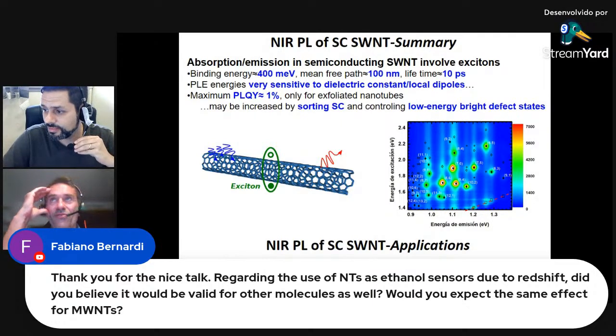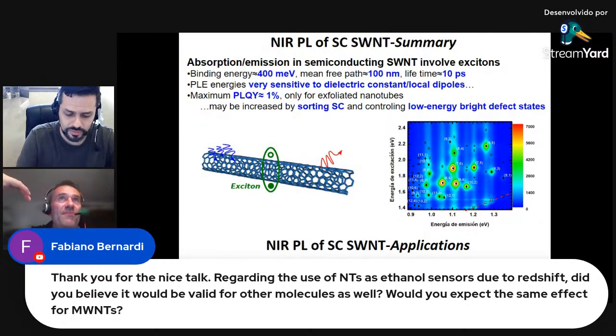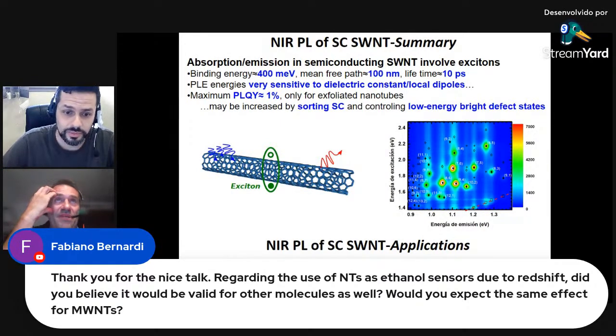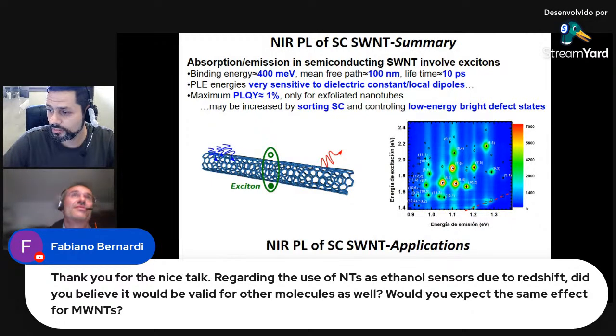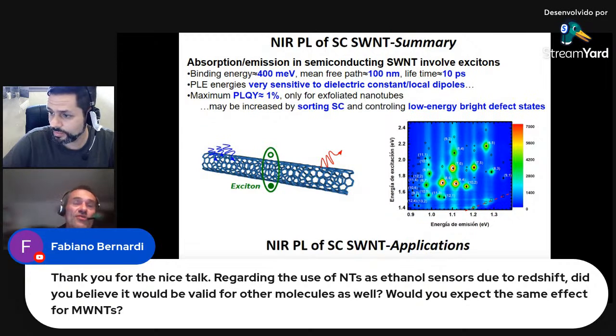Okay, so hi, Fabiano, and thank you for your question. Yes, it's clear that when you start from nanotubes dispersed in vacuum, you have the most blue-shifted spectra that you can expect. And as soon as you adsorb some molecules and form some dipoles on the surface of the nanotubes, you will expect a change in the photoluminescence, which will basically always be a redshift. So whatever molecule you adsorb on the surface, you should be able to detect it. Then, of course, it's not very selective, so there is no way of knowing exactly what kind of molecule you adsorb. You can only calculate the effective dielectric constant, the effective polarity of the molecules that you put on the surface.